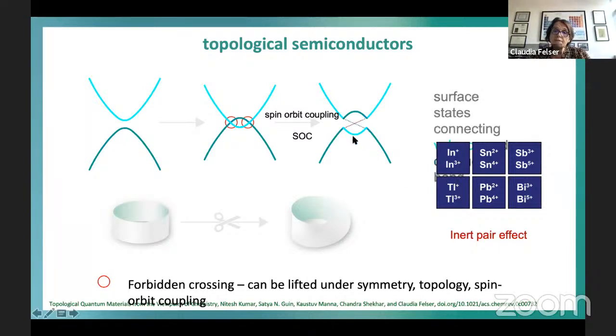And then if you have this band inversion, the conduction band in the valence band and vice versa, you get new kinds of surface states which are spin polarized. For the surface states, we have spin-momentum locking, two different spin polarizations. These are very special surface states which are topologically protected.